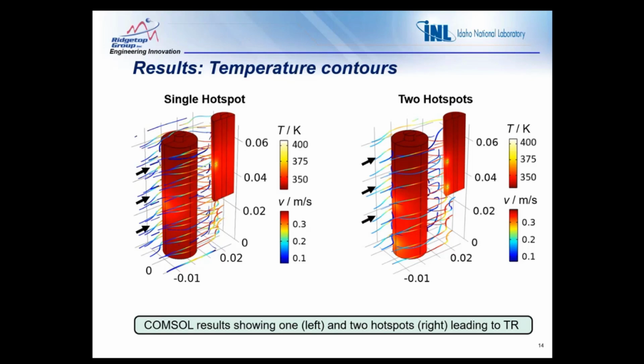And for the two hotspots case on the right, we observe that the temperature contour highlights multiple zones of elevated temperature. The increased heat release from the two hotspots accelerates the rise in temperature and reduces the time to thermal runaway compared to the single hotspot case. The arrows represent the cooling airflow distribution around the battery.